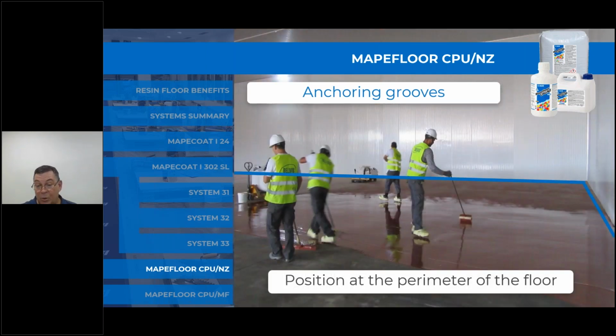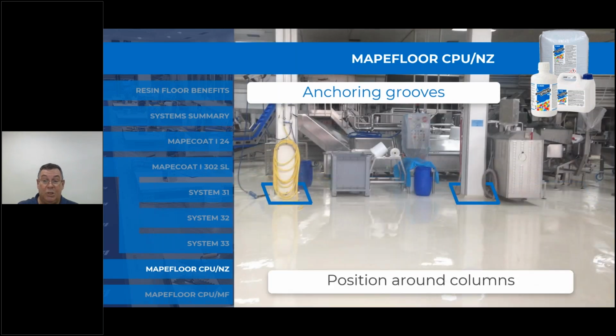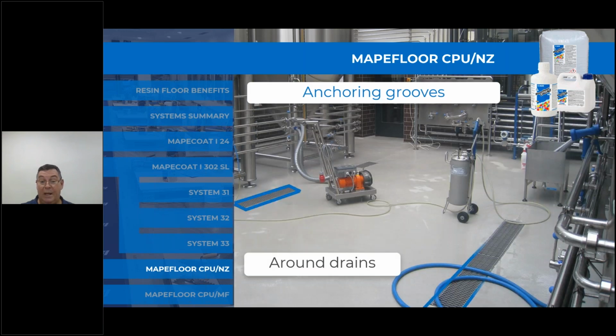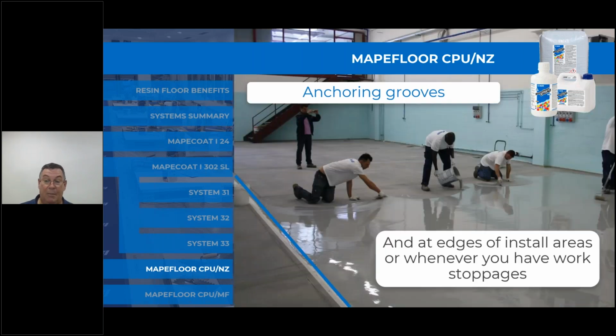And the positioning at the perimeter of the floor. So in a room as shown here, a cut is applied 50 to 100 mil in from the boundary, from the wall. There's also anchoring grooves around any penetrations or columns, and also around any drains. And of course where you terminate the floor at the end, or when flooring is finished for the day and it's going to come back later on to do more of the floor, then an anchor groove is also applied at that point when the work stops.